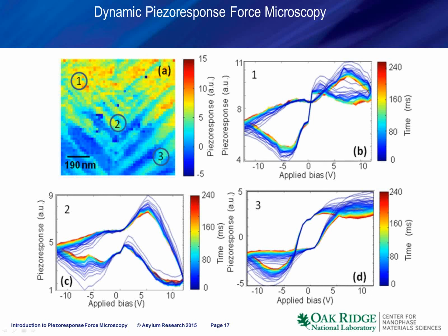However, once we acquire and process this data set, we can get very fundamental insight into the polarization switching mechanism. For example, we can visualize the switching behavior at each location as a series of time-lapsed hysteresis loops. So in this case, the blue loop is the one measured immediately after the pulse, and the red loop is the one where we waited for a quarter of a second. And you can see that in some regions of the voltage space, the blue and red and all the in-between loops coincide, so there is no appreciable time dispersion.